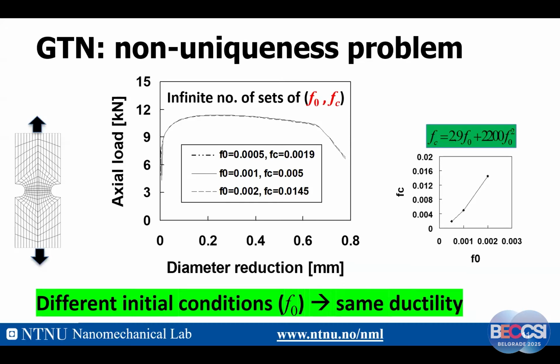And because of this incompleteness problem, there is another problem called the non-uniqueness problem. For a given specimen, you can find an infinite number of sets from F0 to FC, which give identical or almost identical curves. So in fact, you can have an equation: FC will be equal to a function of F0. That means the problem is that different initial conditions can lead to the same ductility.